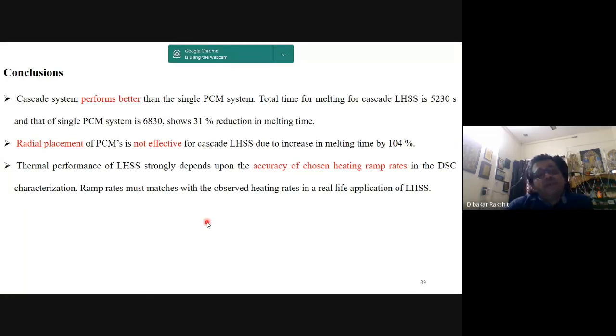So the cascaded system, of course, in comparison to the single phase change material system, outperforms. They work better. The total time of melting for this cascaded system was judged, and it was found to be around 5,000 seconds in comparison to the single phase change material system, which was around 7,000 seconds. So there is a reduction of 31% in the melting time when we are speaking about the cascaded system.